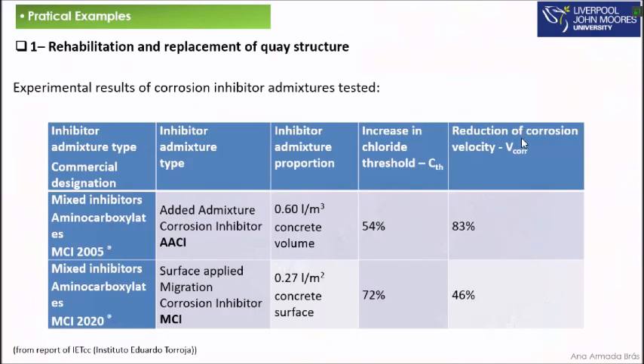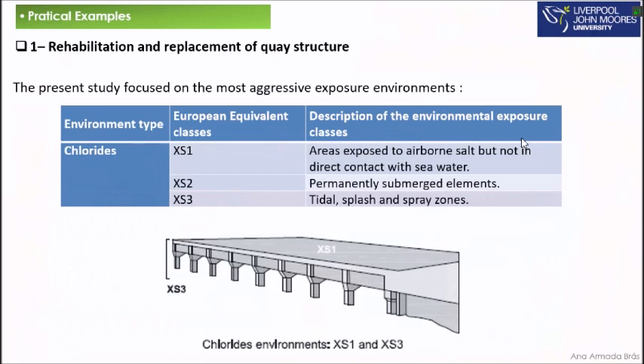Okay, so these are the experimental results of the corrosion inhibitors tested. As you can see, it is expected an increase in chloride threshold of up to 54% for AACI and up to 72% for MCI, and a decrease of the corrosion velocity of 83% using AACI and 46% for MCI. So the present study focused on the most aggressive exposure environment.